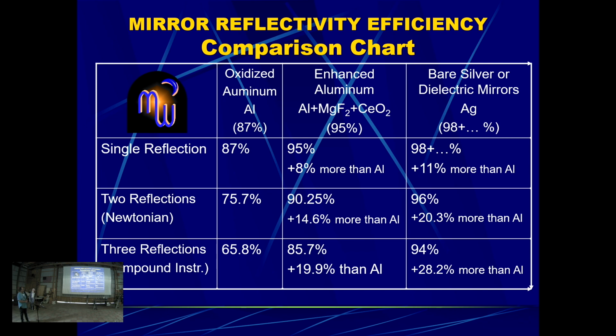Enhanced aluminum at 95%, two reflections will give you 90% efficiency. That's quite a bit more, right? Now silver, wow, look at this, 98% for a single surface coating. With a 2 reflection system, we're down to 96%. Very high, very efficient.